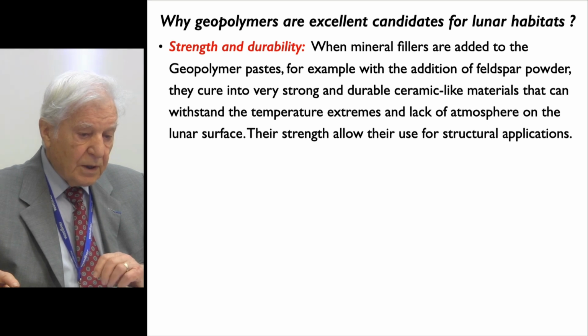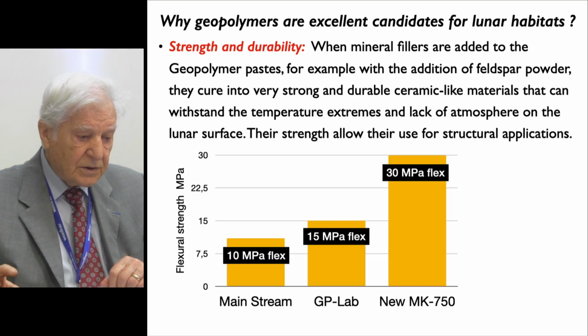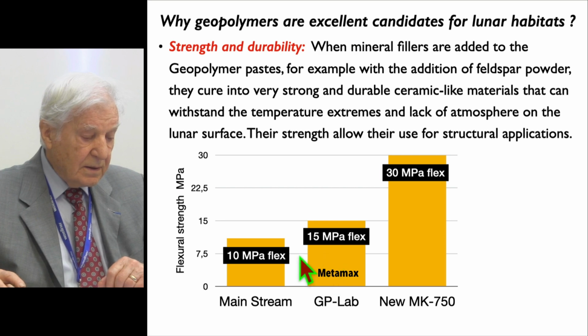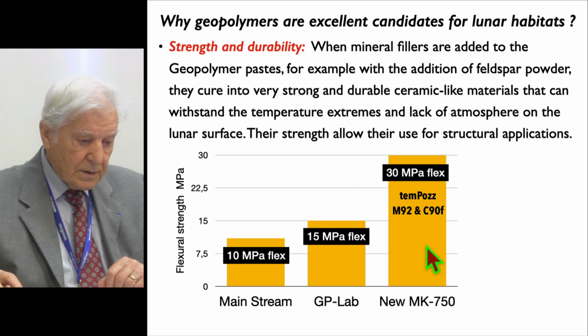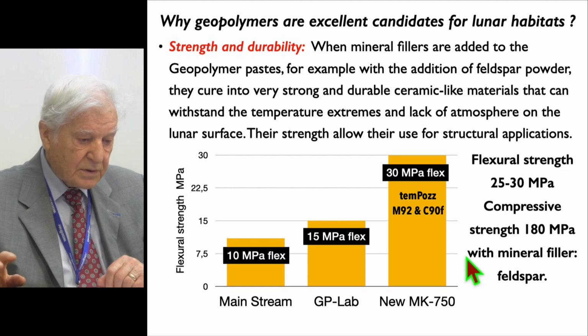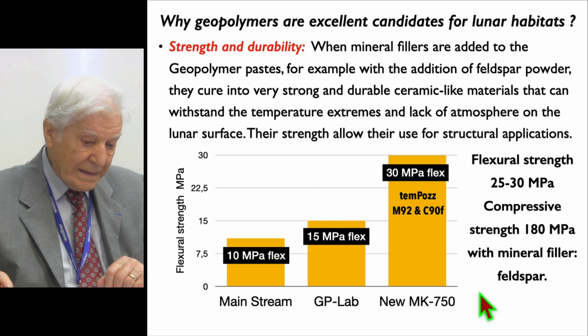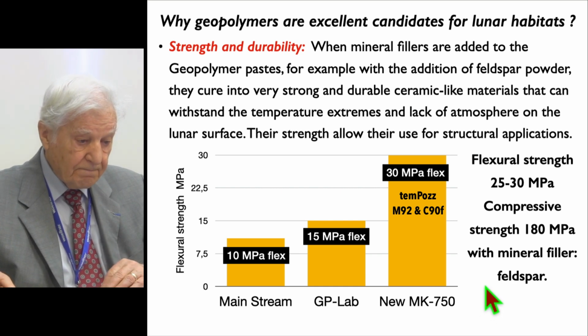During this study, we came across a series of metakaolins which have very high mechanical strength. I repeat what I have already said, but this is important: this was achieved without the addition of fibers. In the literature, that is the mainstream, the flexural strength is 10 MPa. In our lab, for all-purpose commercial metakaolin like Metamax, the flexural strength is 15 MPa, and these new metakaolins have a flexural strength in the range of 25 to 30 MPa and a compressive strength of 180 MPa with mineral fillers like feldspar.